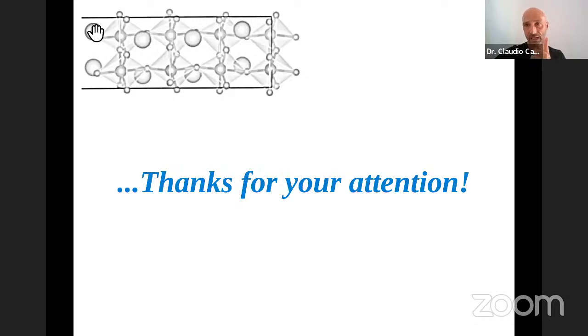You have the electrostatic effects, or in other words, the effects from the electric field that develops in the interior of the materials, but also you have all the surface effects that we take into account by doing these slab simulations, etc. Right? Also the anisotropy of the material, anisotropic piezoelectric properties, etc. Right? So the simple model only disregards all these other effects, only takes into account the electrostatic, but in reality, of course, the other effects can also be important.